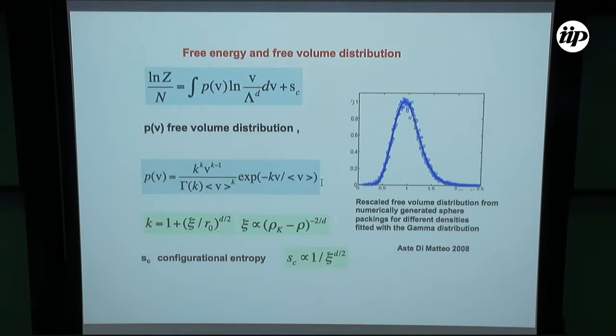So the dynamical length diverges at rho k with this exponent 2 over d, and this S_c comes naturally as it goes to 0 at rho k in this way, exactly as happens in the random first order transition. Just to see that everything is quite coherent. Of course, I did not give you the details, otherwise I don't think I would have enough time. And this free volume distribution has also been found by Aste and Di Matteo, not only in numerically generated sphere packings, but also in real packings for different densities. And they follow, in fact, this gamma distribution.